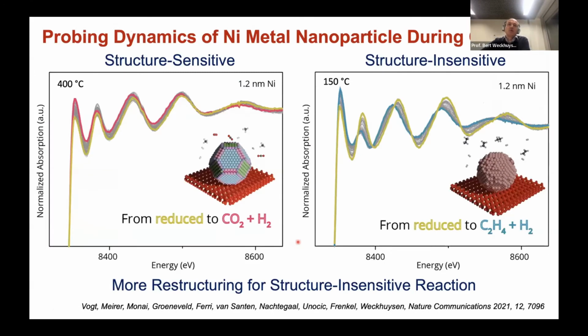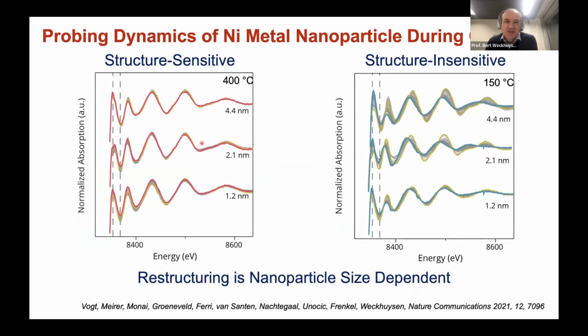Nevertheless, what you can do is now compare these structure sensitive with structure insensitive reactions, for CO2 and hydrogen, or with ethylene and hydrogen. You do not have to be an expert to see that here the differences are less than here. But in any case, some restructuring is going on, and this restructuring is nanoparticle dependent. You can see clearly that these differences are not exactly the same for each metal nanoparticle. So this already indicates that there is metal nanoparticle restructuring, and it is size dependent and reaction dependent.